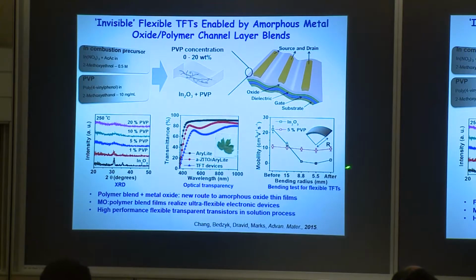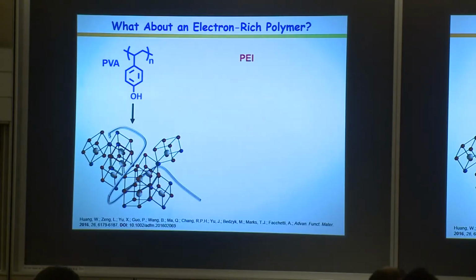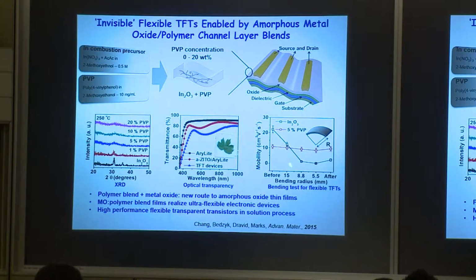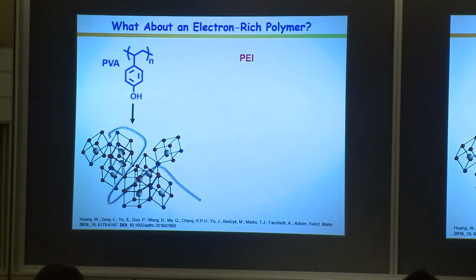Mobility, as you bend the material, this is indium oxide, by the way. With just the indium oxide grown on plastic, it cracks. On the other hand, the material with PVP and the indium oxide is quite robust and flexible. And there's some mobility. Yeah, and the mobility is quite respectable. It's around 10. But let's go one step further.